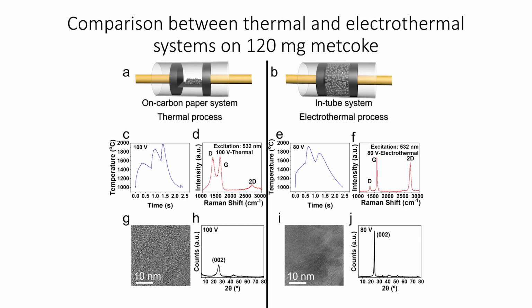Well, it does tremendously. If you put in 100 volts through this and look at the temperature versus the time, the temperature in this sample hit 2,000 degrees. If you look at the material, you get very little graphene. You don't see a big 2D band at all. This looks almost like an amorphous carbon. But if you only put in 80 volts here, you can hit 2,000 degrees and you get very nice flash graphene. So even at a lower voltage, when you're driving a current, you're getting good graphene. And again, this is shown in the TEM and in the X-ray diffraction. You have amorphous material here, and here you have good crystalline material, and by the XRD, good crystalline material.